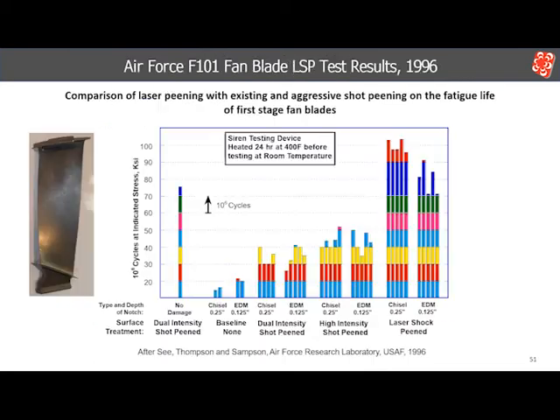Years later, the Air Force did their own evaluation of the process. These are their results. The Air Force compared damaged blades given different surface treatments and 2 different types of damage to a new blade. The surface treatment conditions were dual shot peening applied to new blades at that time, high intensity shot peening, and laser peening. The 2 types of damage were a sharp chisel pushed 6 millimeters into the leading edge and a 3 millimeter deep cut by electrical discharge machining. The chisel damage had heavy plastic deformation at the notch tip, while the EDM notch had none, but instead had a thin re-solidified layer, probably containing small shrinkage cracks with some tensile residual stress.